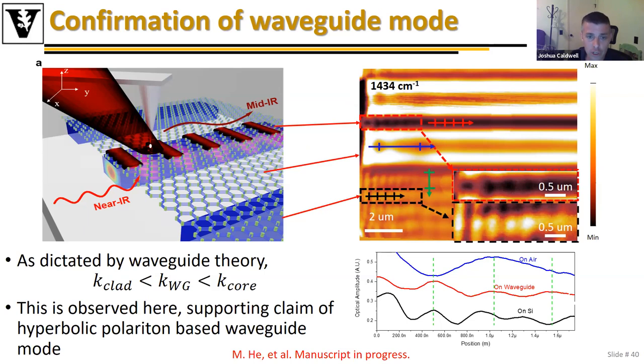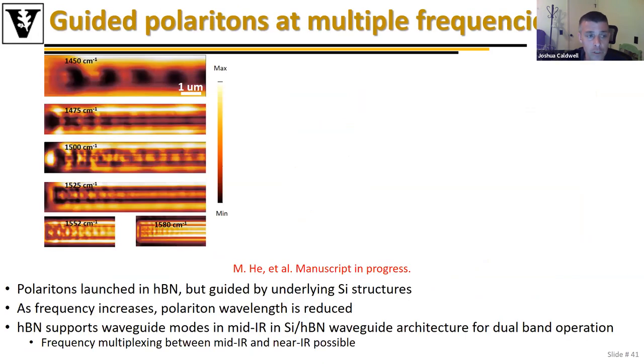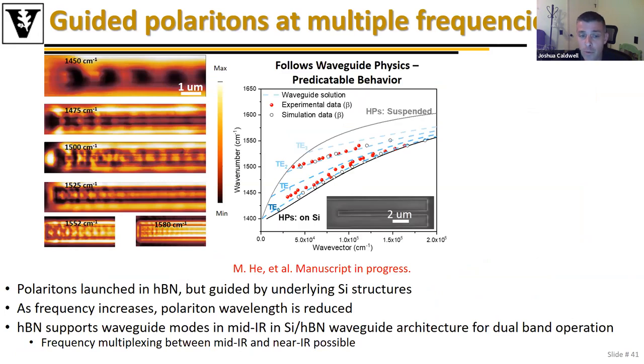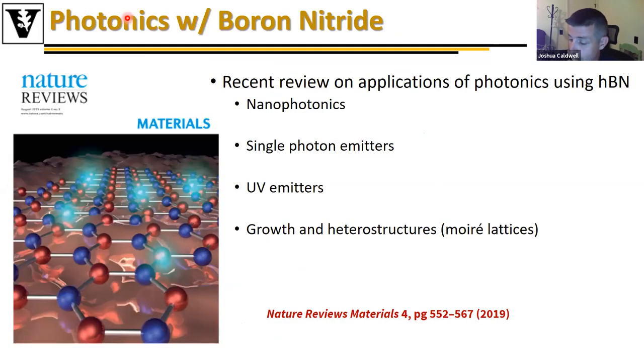And I don't have much time, but I will show that this is certainly operating as a waveguide mode. We looked at the frequency dispersion of this and compared this to analytical expressions. This is currently submitted work where you can see the first and second order waveguide modes that fall in between the dispersion of the boron nitride modes on silicon versus those on air. And so this truly behaves like a waveguide. It also will propagate around curved trajectories. This will eventually show up. I don't know what's up with my computer today, but we've shown that it works around curved trajectories and therefore can be incorporated for a number of different applications.